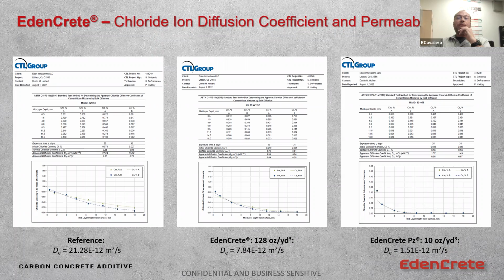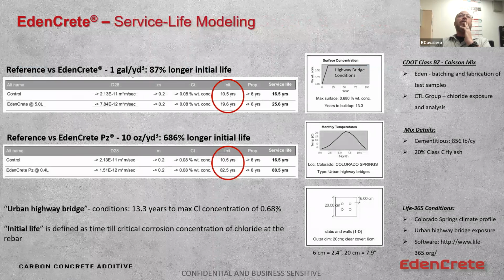One reason why we do this is because you can then take these coefficients and plug them into Life-365 and model service life and years to steel corrosion. When we plug this in, we see that the control mix had a years to critical corrosion of steel of 10.5. EdenCrete extended that by almost 2 to 19.6. When we look at service life, the service life was extended from 16.5 to 25.6.